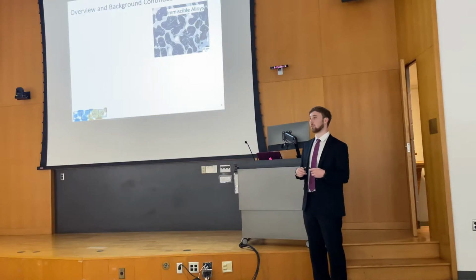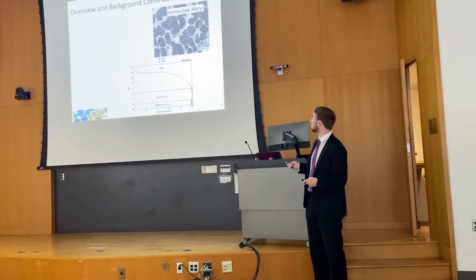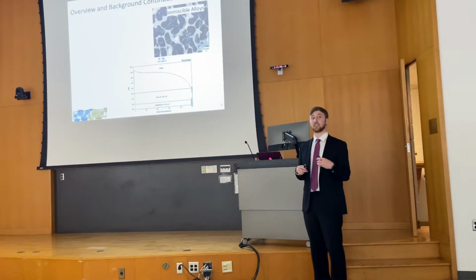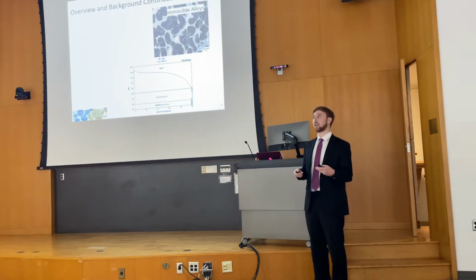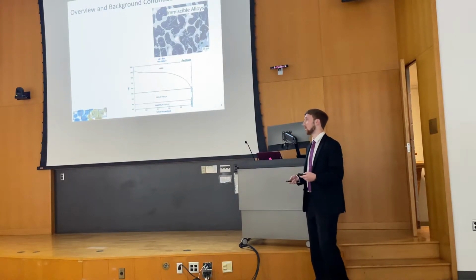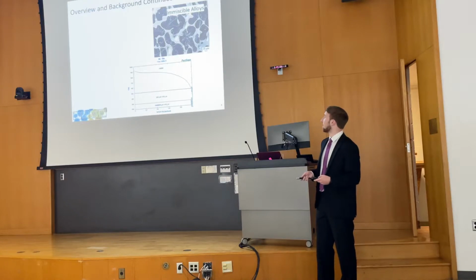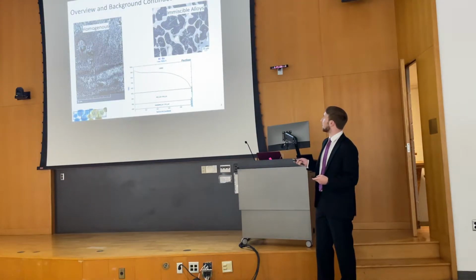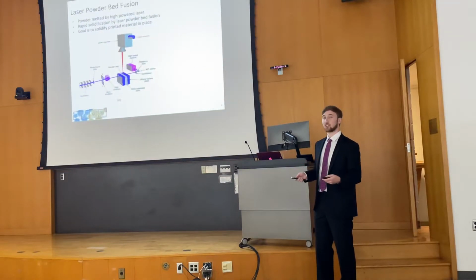component phases due to a large miscibility gap in their phase diagram, as you can see here. They like to separate out. This is because of changes in liquidus temperatures, as well as density and surface tension and their crystal structure. Now, we wanted to make this look more homogeneous like this. And there are two ways to do that that are commonly researched.